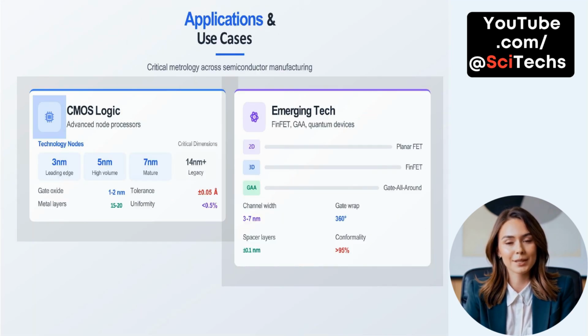and metrology teams. Applications and use cases. Accurate metrology plays a vital role across different segments of semiconductor manufacturing. In CMOS logic, which powers advanced node processors, technology nodes have progressed from 7 nanometers to 5 nanometers and now to 3 nanometers. These shrinking dimensions bring increased complexity. For example, gate oxides now measure just 1 to 2 nanometers, while metal layers may number between 15 and 20 per chip. With such dense architectures, tight tolerances of plus or minus 0.05 angstroms are required, and film uniformity must stay below 0.5%. Metrology must be extremely precise to meet these demands, ensuring high performance and yield.